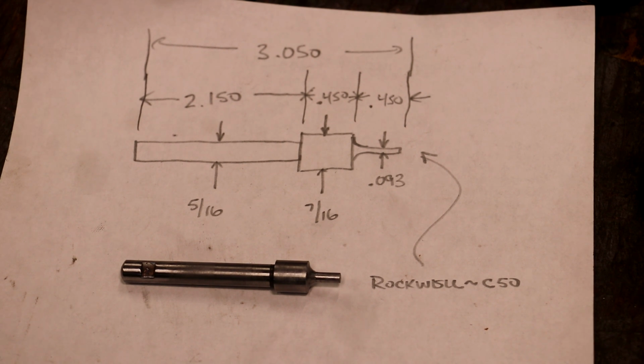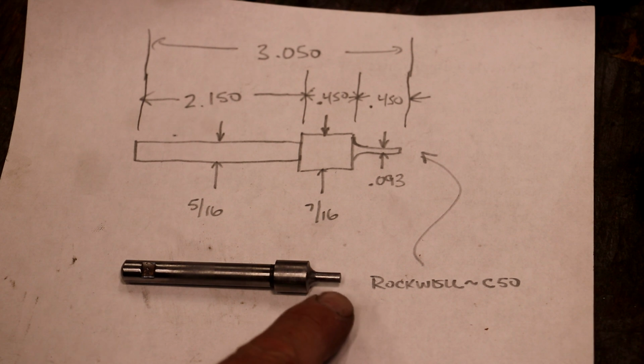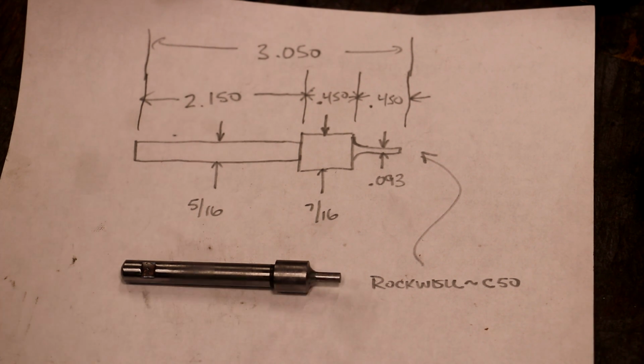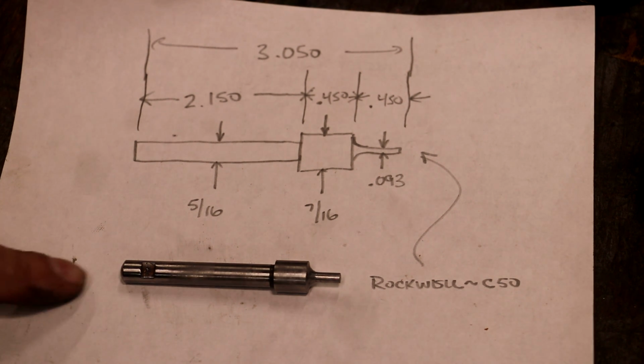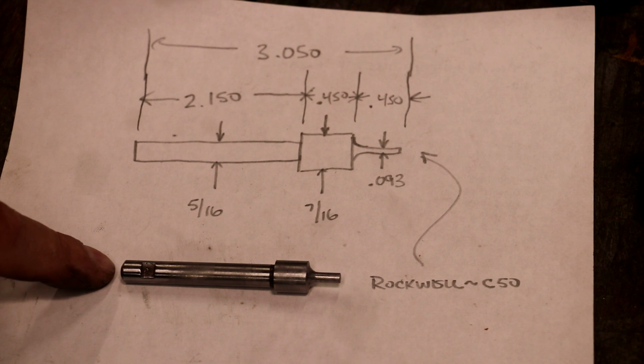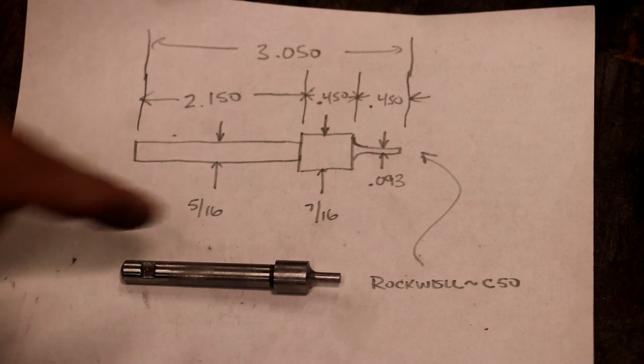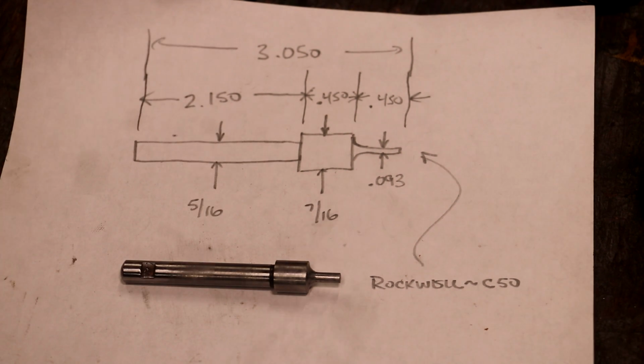I went over and tested the hardness on this end. I made a little dimple on the very tip of that probe there, and it came out about Rockwell C50, which is fairly hard. Interestingly, I did the top, and it's much softer. So it looks like they did a heat treat on this, probably just treated that end down there, and didn't bother with everything else. And after a little bit of research to get to Rockwell C50,